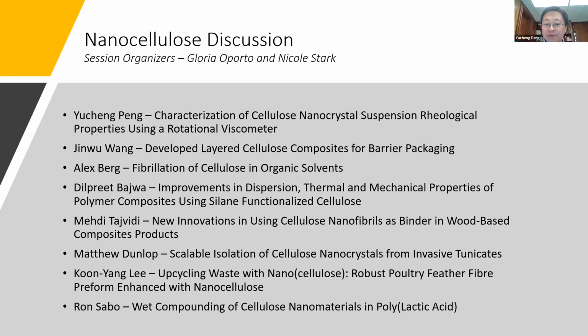It's a short, simple study, but we demonstrated that the rotational viscometer can be used to characterize the cellulose nanocrystal suspension in the lab or in the production plant. It's easy to do, and you can get a pretty accurate result. So we concluded that that's a method we can use for the quality control or characterization of cellulose nanocrystal suspension.